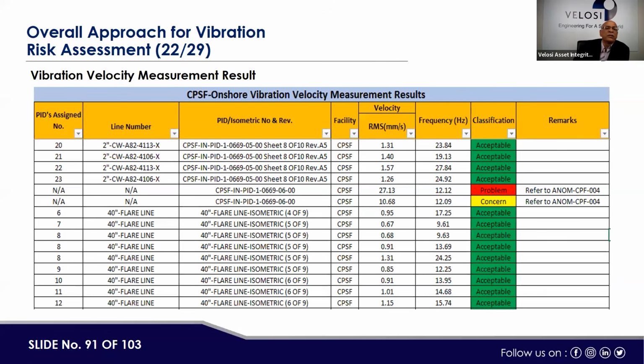For all these locations, we have the P&ID, assigned number, line number, then facility, velocity measurement, and acceptable or not acceptable. So here we can say refer to anomaly CPF04, refer to anomaly CPF04 again, a problem concern, because here the measurement is 27, RMS mm per second is 10.68, all other were considered acceptable. So this way, these results were recorded for all the suspected piping systems and the flare lines as well.